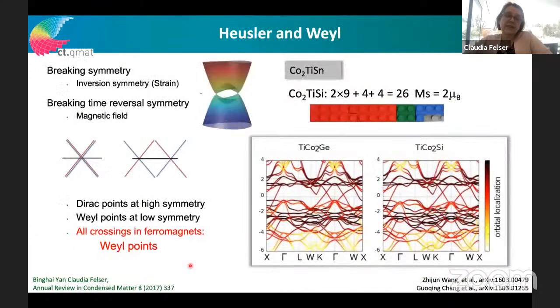In 2017, people recognized that crossings in ferromagnets are Weyl points, and Andrei Bernevig and his team recognized that these half metallic ferromagnets do not have so many bands around the Fermi energy, like here in cobalt 2 titanium tin, and they saw nice crossings. They wrote a very nice paper, and others too, predicting that these are magnetic Weyl semimetals. This was really exciting at the time because people were looking for magnetic Weyl semimetals but had not found them. They predicted something in iridates, but iridates are oxides, and in reality they were insulating and antiferromagnetic,